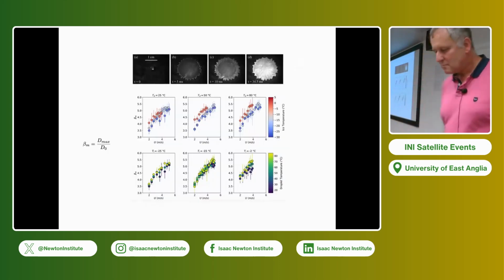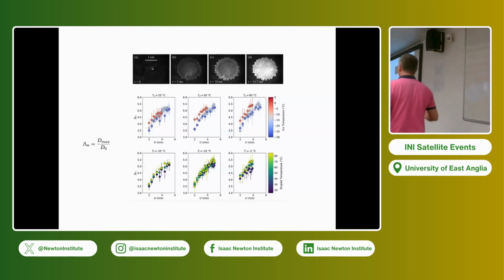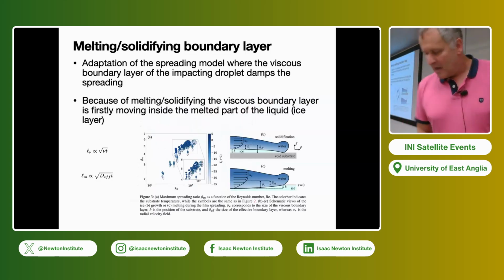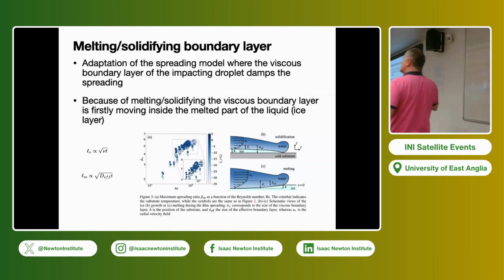Okay. So we can again measure the maximum diameter divided by the initial diameter as a function now of the impacting velocity and the temperature of the substrate, the temperature of the ice, the temperature of the water. And we can try to redo the model that we had before. If you remember, the way we were understanding the maximum diameter was to say, I have a viscous boundary layer that grows from the substrate, and when this viscous boundary layer meets the free surface, you stop the spreading, and it gives you a criterion for the maximum spreading radius.